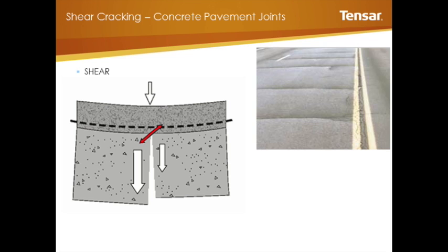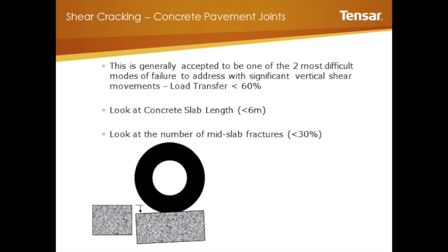And then with time, you know, I'm based down here in Louisiana at the moment, they have experience with 20 to 50-year-old slabs, and clearly you get loss of serviceability with respect to load transfer, and you can end up with structures sitting at 30 to 50% load transfer, which is typically a failed condition, according to AASHTO, where I think everything up to 60% is probably in a relatively poor condition. So what's important here, because this is such a severe distress type, is to understand what the associated boundary conditions are. Because it's such a severe distress type and we're specifying load transfer, not a lot of people go out and measure it.